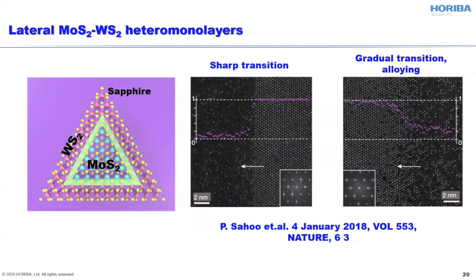So now we'll talk about the hetero-monolayers of these transition metal dichalcogenides. So luckily, chemists and material scientists figured out quite some time ago that it's absolutely possible to synthesize this sort of materials. And of course, one can imagine that in an ideal world, we would like to have full control of the interface between material A and material B. And sometimes, as we can see in these TEM images, we can have almost atomically sharp edges, but more general and probably the most abundant situation in the synthesis of these lateral heterostructures is the situation when we have a gradual transition from material A to material B, thus having some sort of alloyed area.